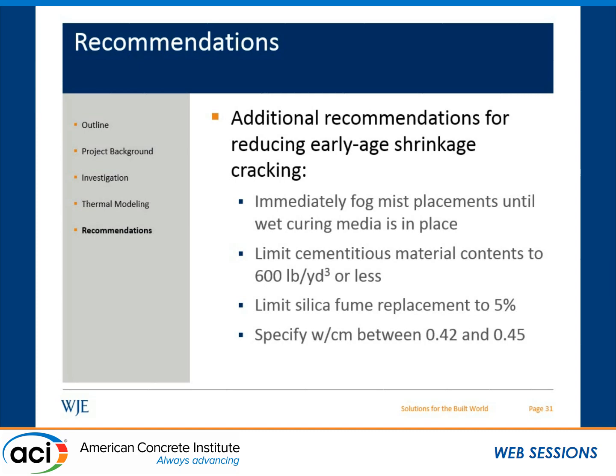This was not part of their current curing specifications, but they're going to be adding this to it. We also recommended limiting the cementitious material contents to 600 pounds per cubic yard or less. Some of these mixes had very high cementitious materials contents, which only exacerbates a lot of those early age shrinkage problems. We also recommended limiting the silica fume replacement level to 5% to help combat some of that early plastic and autogenous shrinkage. And we also specified a maximum water cement ratio between 0.42 and 0.45.